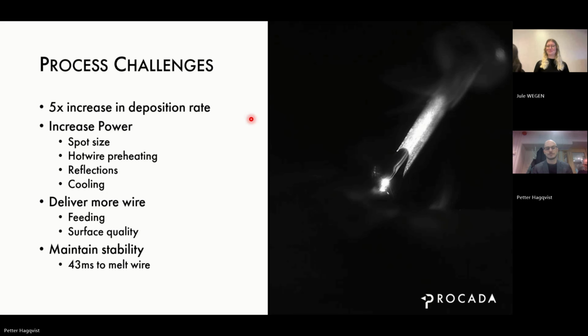So we need to increase the power, deliver more wire, but we also need to maintain the stability. Because if we don't, we could agitate the melt pool, or we could not properly melt the wire and thus introduce defects. And as a measure of this, we have 43 milliseconds to thoroughly melt the wire from when it enters the melt pool until it otherwise would hit the bottom of the melt pool and interact with the substrate, giving us an LOF. So that's more or less the time scale that we're working at. And the faster we feed the wire, if we were to double the feed rate or the production rate, this would go in half unless we change the diameter of the wire.